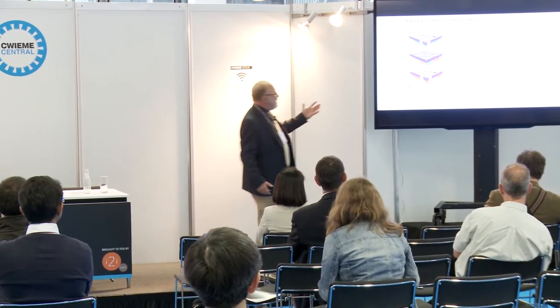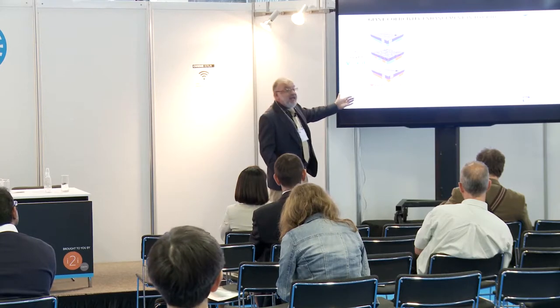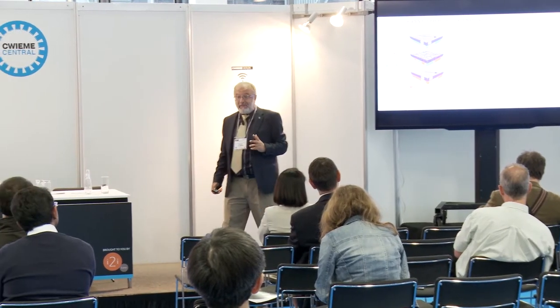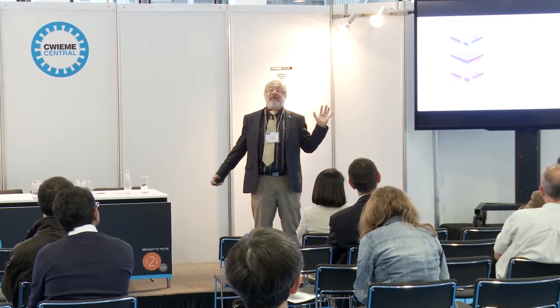For reasons which I cannot get that technical about, but they are easily explainable, because of the interface between this vanadium oxide and the nickel, the coercivity can change by as much as a factor of 5 in a very, very narrow temperature range. Now, from a scientist's point of view, this is a dream, because this is what you want to do. You want to find something that nothing else does.